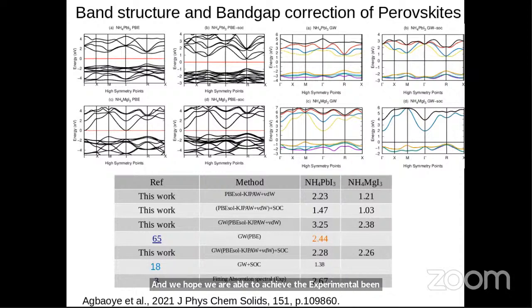So here in the table, we did a lot of work, and this is for ammonium lead iodide. We're also trying to see what difference we get from ammonium instead of tetramethyl ammonium lead iodide. So here we use the PBEsol functional. Also, we use van der Waals correction, and we're able to achieve a band gap of 2.23 electron volts as the DFT band gap. So when we use spin-orbit coupling, we realize that the band gap reduced to 1.47 electron volts. And when we also use GW on the same material without spin-orbit coupling this time, we are able to